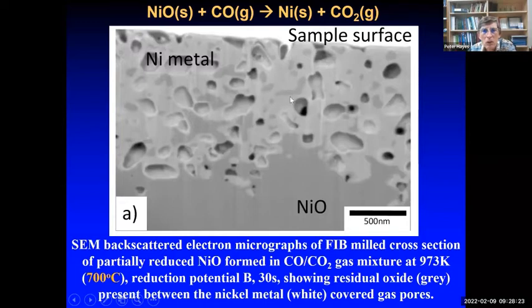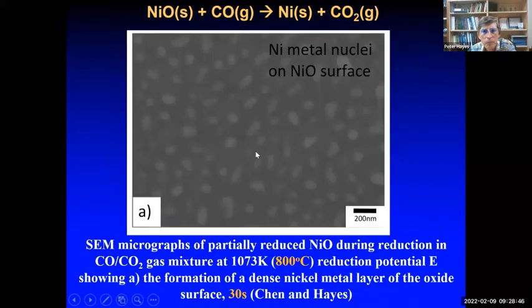So you can see there's some nickel oxide encapsulated in a dense nickel layer, which is formed around there. So the gas is going all the way to the nickel oxide interface, but it's being covered by a dense nickel layer over the surface of the pores.